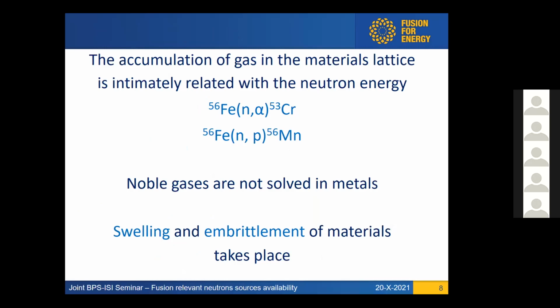And this is the problem. The accumulation of gas in the material's lattice is making swelling of the steel, with the difficulty that noble gases are not soluble in metals. That's why we tend to go to reduced activation ferritic martensitic steel, the RAFM, that possibly you heard about, for fusion reactors, as a solution to accumulate this alpha particle, this gas, because the ferritic martensitic steels themselves hold some kind of interstices, some kind of volumes, which allows the accumulation of the gas. And the swelling, which can be very substantial for austenitic steels, leads to rapid embrittlement of materials.